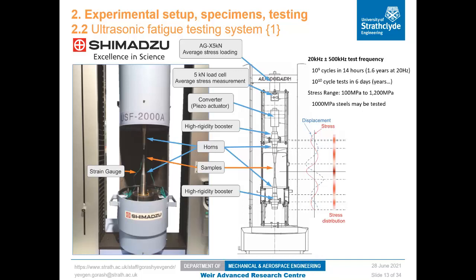This particular arrangement also included a 5 kilonewton loading frame that allowed us to do fatigue testing at different R ratios. The expectation was to reach 1 billion cycles in 14 hours, when at the same time you would need 1.6 years to get to that value at 20 Hz using conventional fatigue testing.